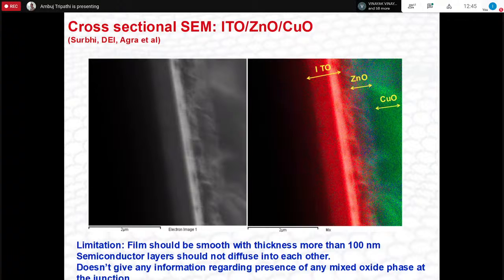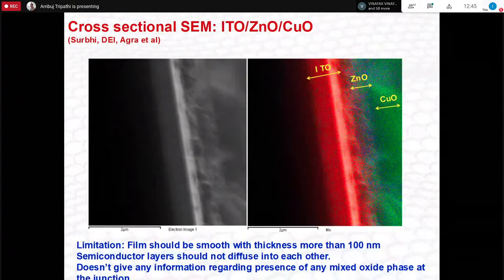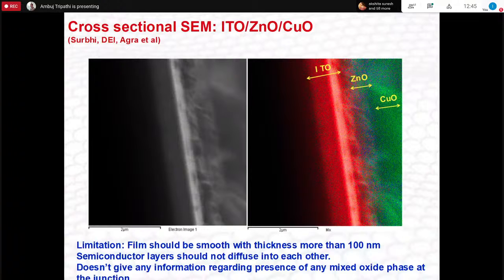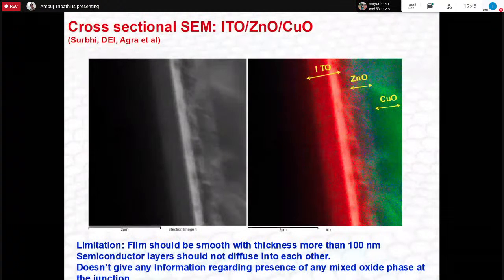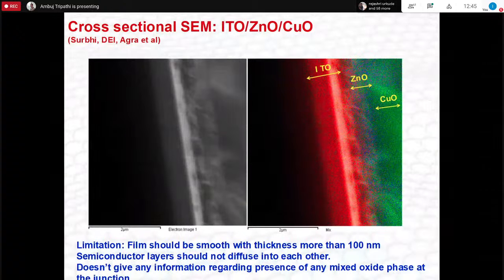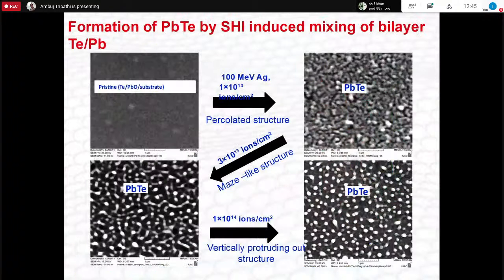You can do it at different levels: this is on the ITO substrate, then there's a zinc oxide layer, and then there's a copper oxide layer. So you can do all these measurements and see. The main idea was that they were trying to look into whether there is any oxide phase at the interface or not, because you expect it not to happen.